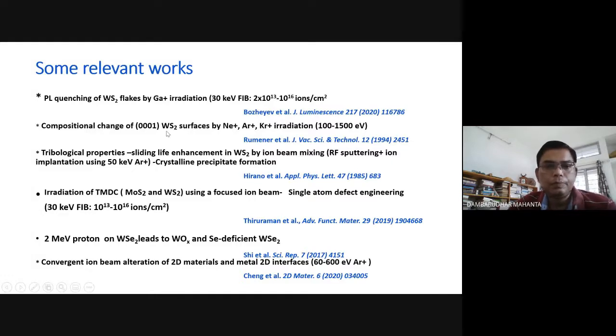Then you have similarly compositional change of WS2 surface by Ne+, Ar+ and krypton irradiation, that is neon, argon and krypton irradiation, from energy range changing from 100 electron volt to 1.5 keV. Now tribological properties, as I mentioned before, sliding measurement, or layers would like to slide over one another, and it has application as solid lubricant. So tribological properties are important to investigate.